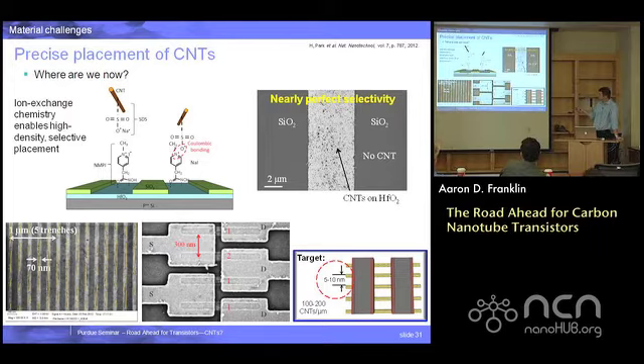But this is one with 70 nanometer trenches at a 200 nanometer pitch. And you can see the tubes like to align up within these trenches fairly well. And if you restrict them in the other dimension, then you can start to make devices at a large scale. And this is the sort of platform we use for testing those 6,000 devices for looking at the purity of the solutions, so that we can nominally make sure we have one nanotube.